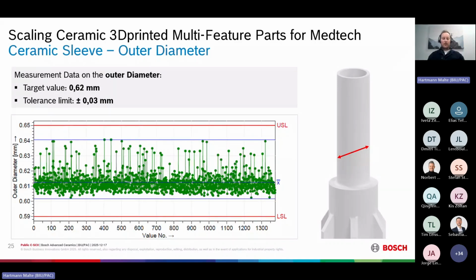If we look back, we see the inner diameter was 0.465 millimeters and the outer one was 0.611 millimeters. So in the end, we actually achieved a wall thickness of only 73 micrometers on the sintered parts.